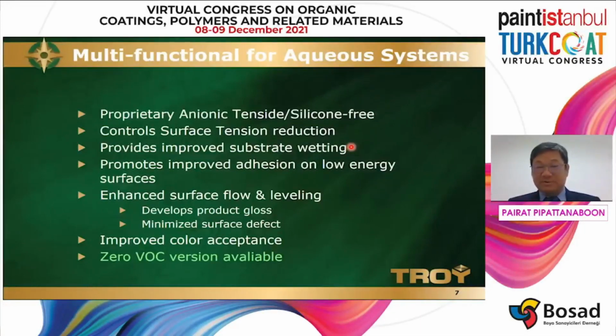So once you reduce surface tension to become lower than CST, critical surface tension, you can improve surface substrate wetting, and that's how you get surface flow and leveling, which improves your gloss, color uniformity, and also minimizes surface defects. And at the end, when you tint the white base, you can control color acceptance or color development. The product is also available in a zero VOC version.